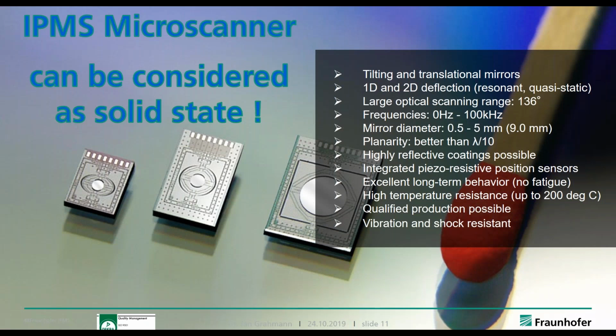So I've showed you we've got tilting and translational mirrors in 1D and 2D deflection. We can do that resonantly and quasi-static. We went so far up to optical scanning range, so field of view, to 136 degrees, which is a very soft mirror then, and 1D, of course. We have frequencies in between 0 hertz and up to 100 kilohertz realized in different designs.